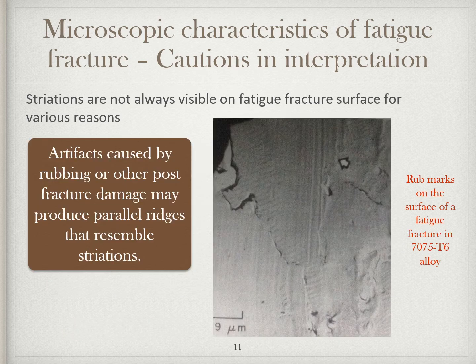Marks resembling striations caused by rubbing or other post-fracture damage may produce parallel ridges that may erroneously be considered as striations. This kind of marks may occur when opposite sides of the fatigue fracture rub against each other during compression loading of a crack. For example, a shaft in a rotating bending has a tensile stress at one position, that is the convex side of the rotating member, while on the opposite, that is the concave side, the compressive stresses tend to rub any existing crack surfaces together. So here in the figure shown over here, we can see these are the rub marks which may be erroneously considered as the striations.